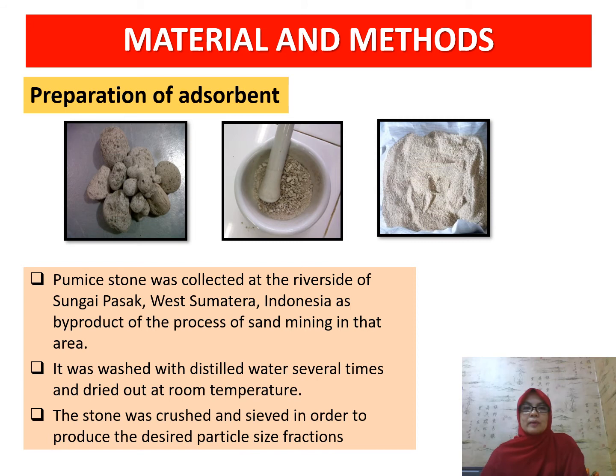Now I want to explain about the material and method. The first one is about the preparation of adsorbent. Pumice stone was collected at the riverside of Sungai Pasak, West Sumatra, Indonesia, as a byproduct of the processed sand mining in that area. Pumice was washed with distilled water several times and dried at room temperature, and then crushed and sieved in order to find the desired particle fraction.